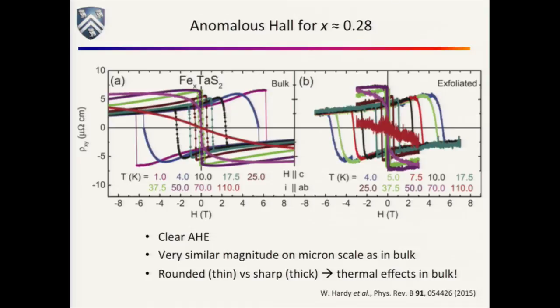And again, I did not bother to show magnetization on the little flakes, because we couldn't do it, you don't have enough signal. But magnetization in the bulk really does look a lot like what you see in the anomalous Hall. That all kind of makes sense. The magnitude of the anomalous Hall resistivity is rather large. These are tough measurements to do, by the way, because the magnetoresistance itself is so huge that if you get the alignment wrong, you pick up a big longitudinal magnetoresistance contribution on top of the anomalous Hall, so you gotta be careful about that. But again, everything looks very similar between these two things.